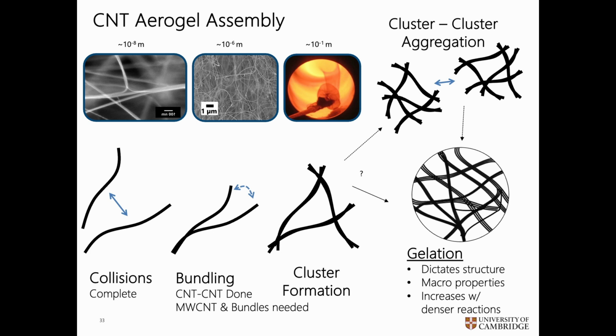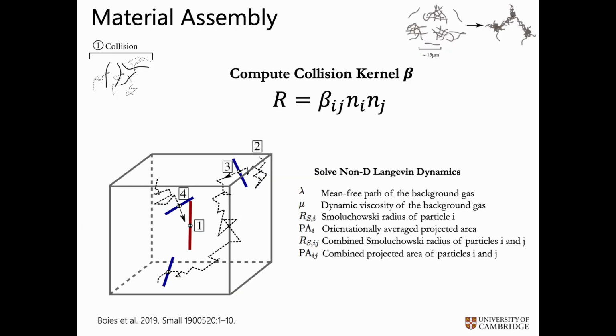And so what happens is that this bundling occurs up to a point, but eventually the structures can't collapse and minimize energy anymore. And once cluster formation is done, you ultimately can go through one of two different pathways that we're not fully convinced of which is the dominant pathway yet. You either get a process called cluster-cluster aggregation, or a gelation that occurs straight from the individual cluster growing larger and larger. And that's what we're spending our time investigating.